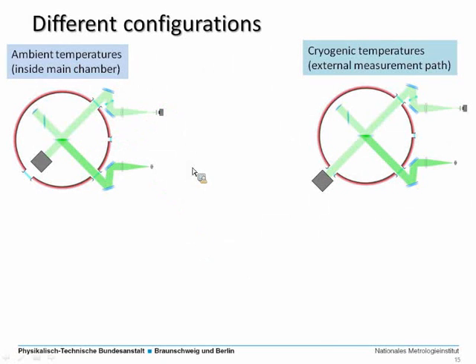Currently we have different configurations which you can use to operate the measurement. The first one is what I've shown on the slide before, around ambient temperatures, say 10 degrees Celsius up to 50 degrees Celsius. We can use this translation stage as a sample holder, and then the whole vacuum chamber can be changed in temperature via a thermostat.